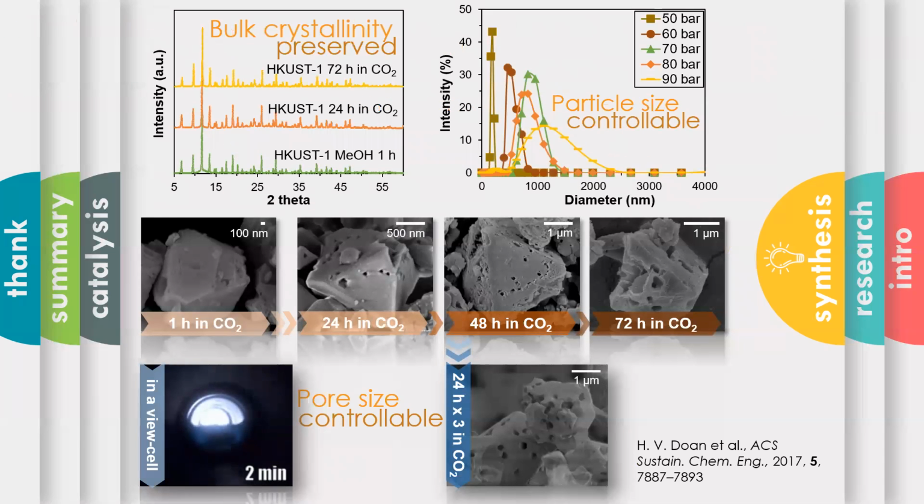We demonstrate that there is a direct relationship between pressure and average particle size, with the preserved framework of the pristine MOF. This finding introduces another factor that we can change during MOF crystallization to finely tune the properties of the porous materials. The possibility of adding larger pores and channels offers exciting prospects for the deployment of MOFs as catalysts.